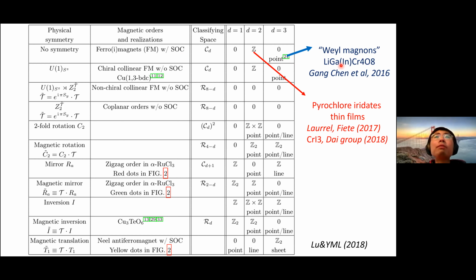This table gives you some idea about where to look for these topological magnons. In particular, you can see that if you have collinear or coplanar magnets without spin-orbit coupling, the classification is completely trivial. This strongly suggests that if you have spin-orbit coupling, it's more likely for you to end up with a system with non-trivial topological magnons. Therefore, we want to look into materials with relatively stronger spin-orbit coupling to identify topological magnons in those systems.